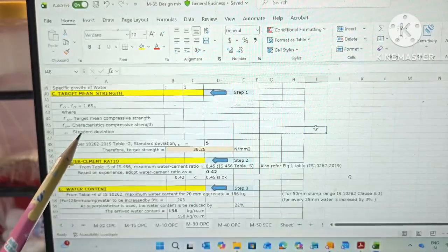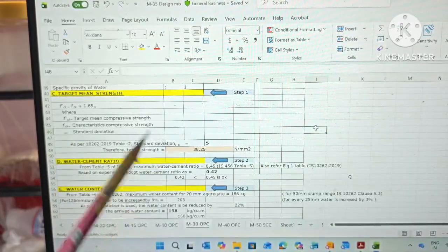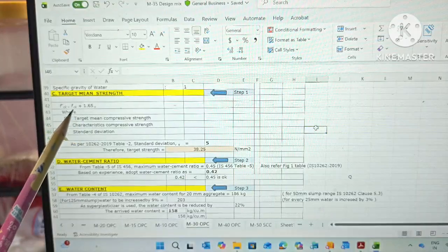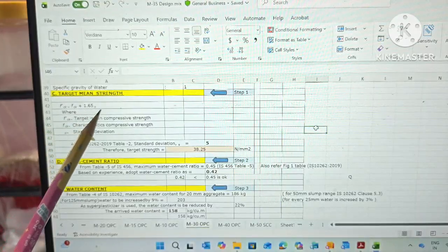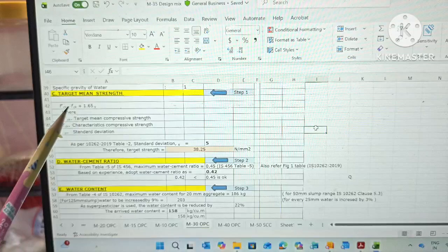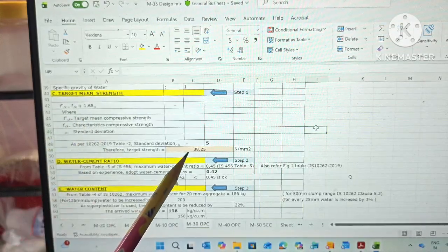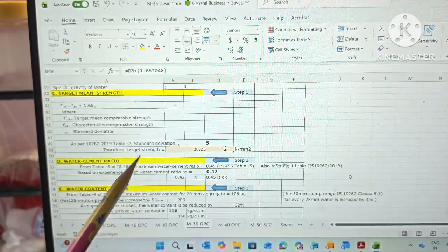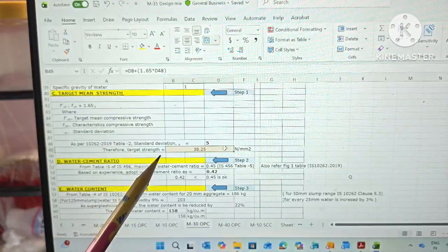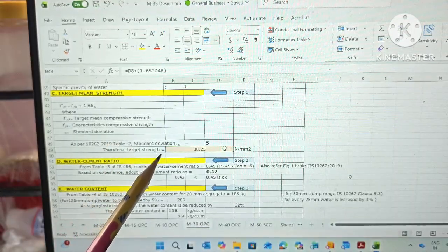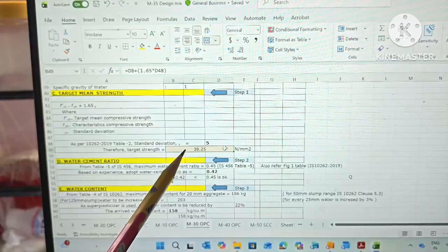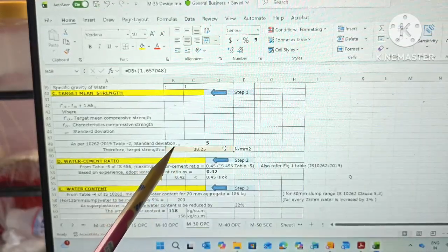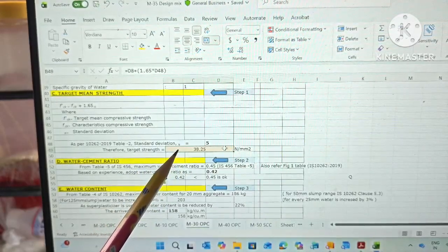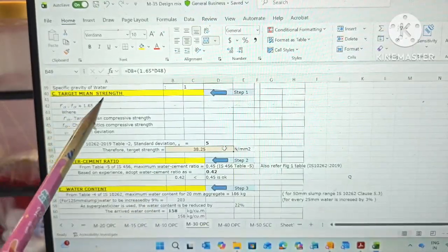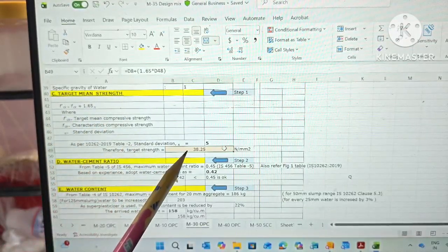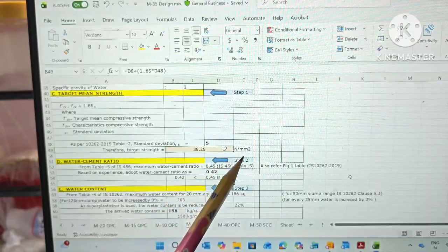Considering standard deviation as 5, we will put the value of S in the given formulation, where FCK is 30 plus 1.65 into S, where S is 5. So when we do calculation of this, we get final answer 38.25. Since this calculation is done in the Excel format, I have set the formulas for it so that you get the direct answer. If you have any queries regarding this, please comment me so that I will explain that part in detail. So target mean strength for M30 grade of concrete comes 38.25 Newton per mm square.